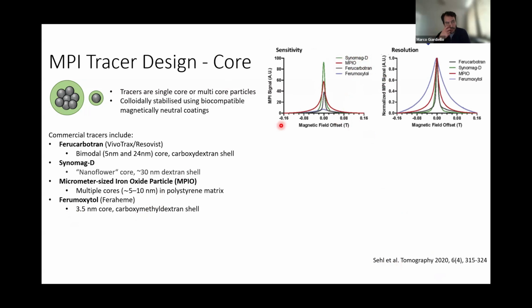I think I showed in the previous slide that anisotropy has a large effect on the magnetic signal, the Néel response to the magnetic signal. And if you've got a nanoflower, you obviously have quite an anisotropic particle. So that's probably why that has such a strong signal. And then the others are, by comparison, not as strong. So the one that is actually provided by Magnetic Insight, relative to others, is not necessarily one of the best ones. And here are all those peaks normalized to show you the resolution of each one.